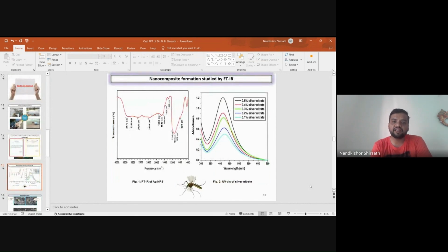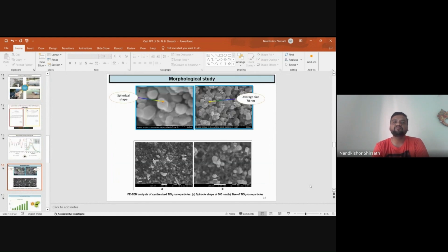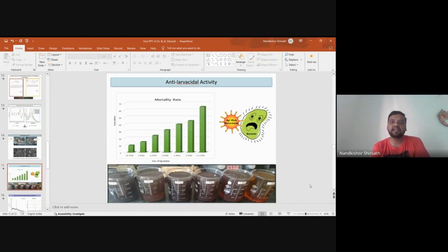Here are the FTIR analysis of the synthesized material and the UV-visible spectra of the silver nitrate. These are the morphological analysis of the synthesized material. As we can see, the synthesized silver nanoparticle consists of a spherical shape with an average size of 30 nanometer. These are the anti-larvicidal activity of the synthesized material.